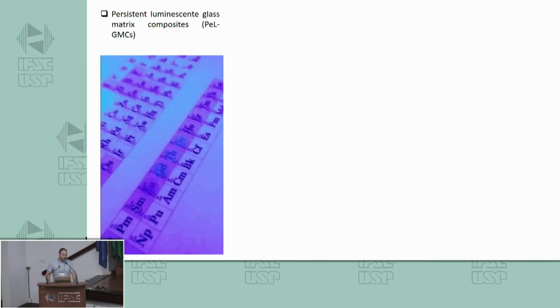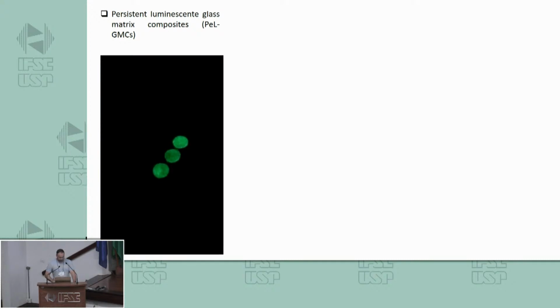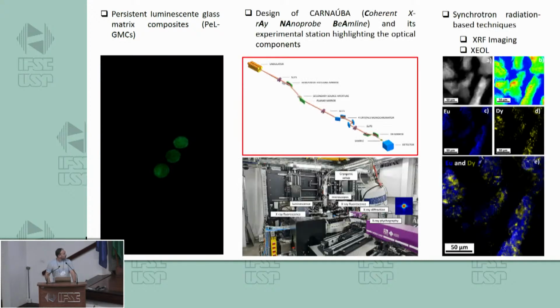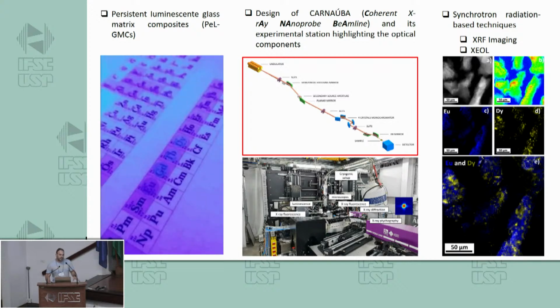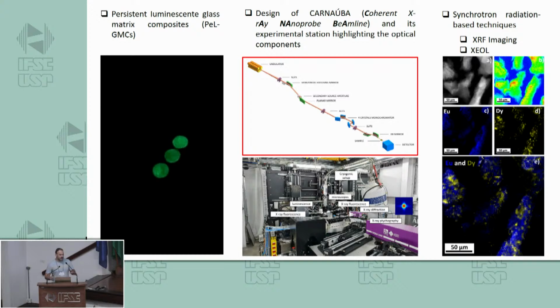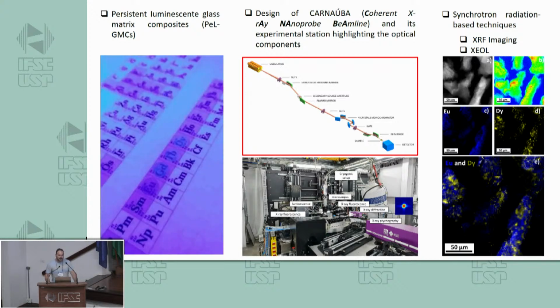And how do we do that? Using synchrotron radiation-based techniques available at the Carnaúba beamline. Carnaúba is an acronym for Coherent X-ray Nanoprobe beamline, and this beamline offers a beam resolution of about 200 nanometers. At this beamline, we have different detectors that allow us to perform different kinds of experiments. For example, X-ray fluorescence imaging in a broad range of energy, and also X-ray excited optical luminescence, nanotomography, nanodiffraction, and so on.